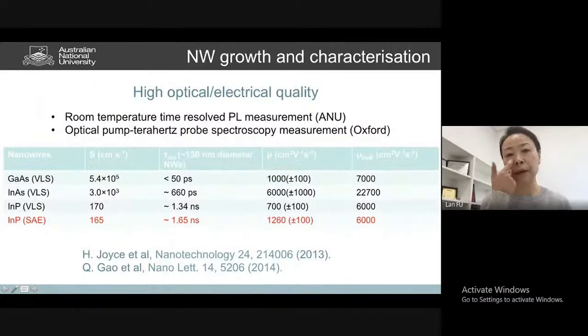And then, of course, we need to do some optical and electrical measurements to evaluate the properties. So we do some time-resolved photoluminescence measurement. Basically using a laser to pump your material to create electron hole pairs and then measure the recombination emission from those nanowires. From the intensity of the luminescence from your material, and if you also measure the line width, you can really tell if the material has good quality. With time-resolved photoluminescence, you can evaluate carrier lifetime, which is a very important measurement for the material, because a longer lifetime means fewer defects in your material, right?